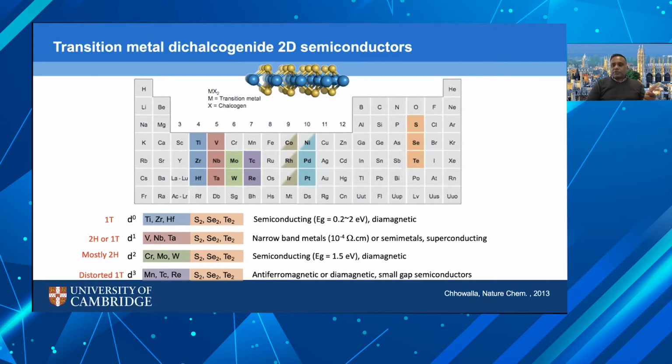kinetics due to the fact that the electrodes are highly metallic, so the conductivity is high, and there's also catalytic activity directly with the metallic scaffold. And also the strong affinity of the polysulfides to MoS2.